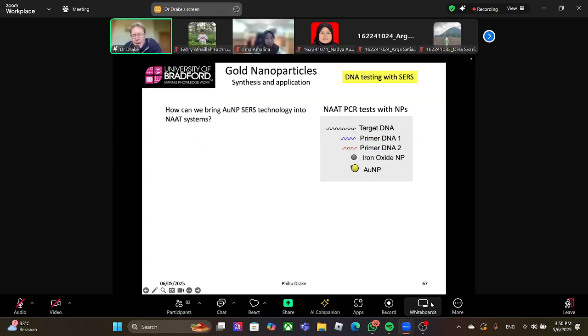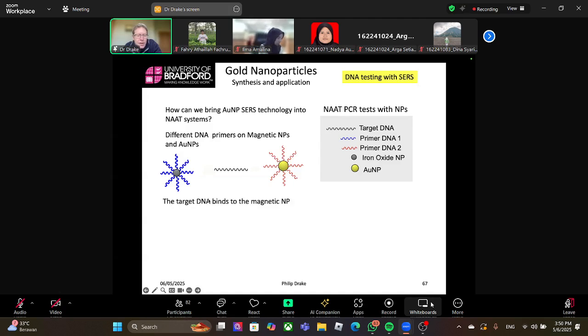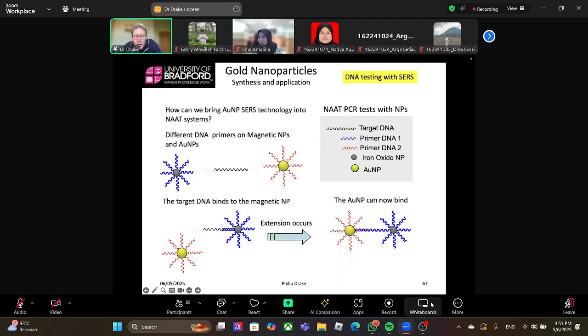So we can use the same iron oxide particles and the same gold nanoparticles, label them with the primers on the surface, and we get a system where we can detect DNA. We take our iron oxide nanoparticle with one of the primers on the surface. Our gold nanoparticle has the other primer. These don't combine together, so they don't interact. They're stable in solution. You add in the DNA you want to detect. When you add it in, that forms double-stranded DNA on the iron oxide particle. Polymerase extension occurs. The polymerase comes in and extends that DNA. Once extension has occurred, the gold nanoparticle can then bind in. So now the gold particle binds in, and you get a complex forming between the gold and the iron oxide. This gives you a magnetic SERS response depending on the concentration of the target DNA.